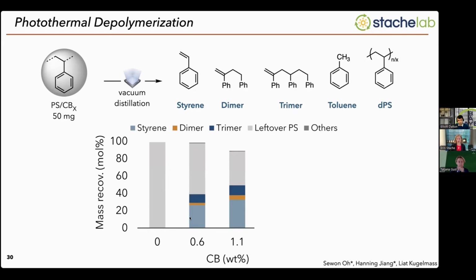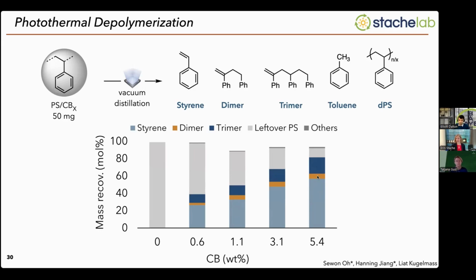As we start to increase the carbon black loading, so even at 1 weight %, we start to see styrene monomer generation, so about 30 or 40%. And then around 5 to 6 weight % of carbon black loading is where we saw most efficient depolymerization to styrene monomer. So about 60% yield of styrene monomer, some dimer and trimer, which are the most common byproducts from depolymerization or polystyrene pyrolysis, and then a little bit of leftover polystyrene.